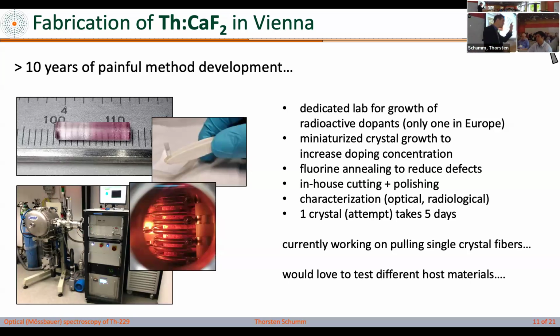Anyways, you've seen the blue trace of fluorescence in the crystal that June showed. That's usually 0.5 millimeter of volume. And if I have such a crystal around it, it's just background and loss of material. So we reduce. And the next step we're currently working on is actually pulling single crystal fibers to make the volume even smaller.